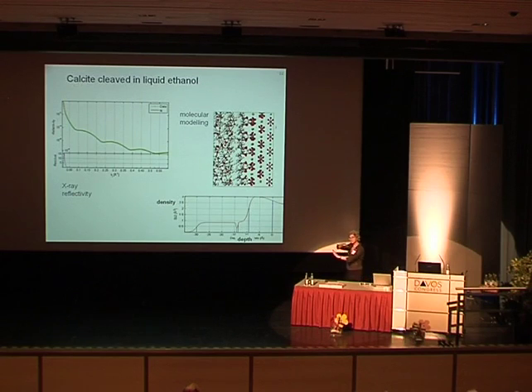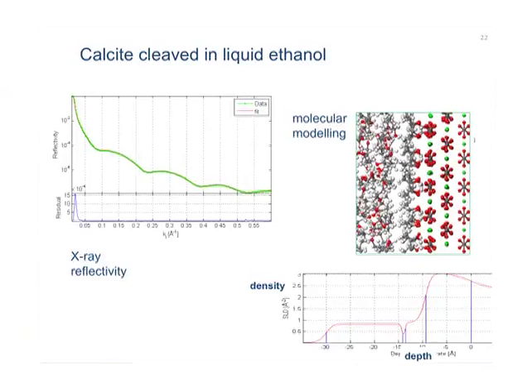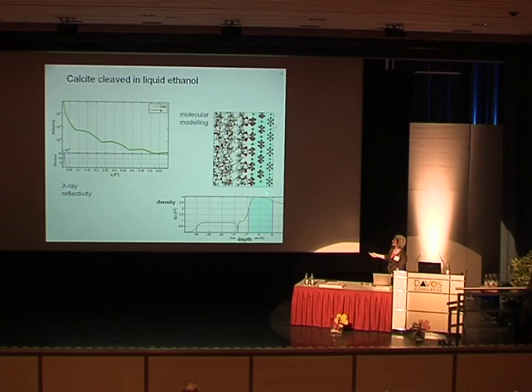And we can also do some experiments with a technique called X-ray reflectivity, where we shine an X-ray off a surface and we measure the pattern that comes out. We collect the pattern and then analyze it. This is the raw pattern with bumps, and these bumps are an indication that there's different densities on the surface. So here we have a cross-section of the surface where we've got the calcite here, and we can compare that with our model. There's the calcite.